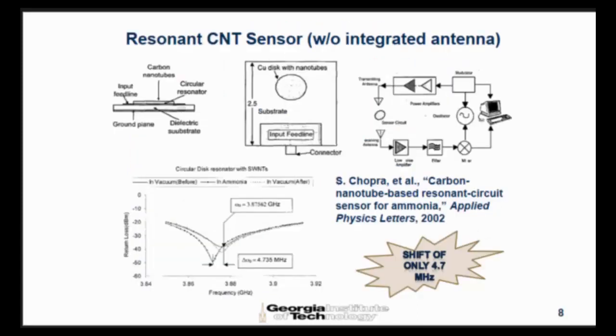So this comes to now. I'll talk about my particular contribution in this paper. This is an example of a paper where, in a circular disc resonator, the entire top surface of the resonator is coated with an epoxy of single wall nanotubes, and they measure the shift in resonant frequency using a network analyzer connected to this coaxial connector. Okay, so you just look at this graph. This is an ammonia detector. The black line is before exposure to ammonia. And once the sensor is exposed to ammonia, because of the surface chemical reaction going on, the resonant frequency shifts to the left by only 4.7 megahertz.